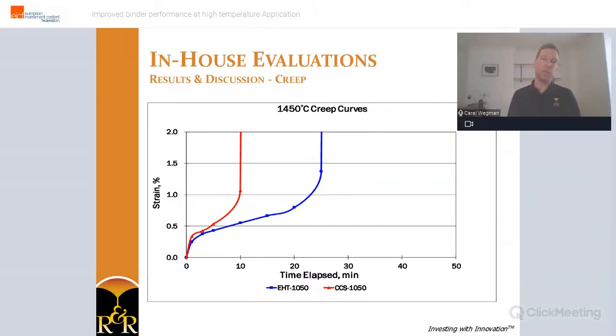So this portion of the creep data was obtained at the high test temperature of 1450 degrees C. In this graph, I only show the data for the samples fired at 1050 degrees C, but it represents the data in general. Both binders show a catastrophic failure. That being said, the EHT sample failed 15 minutes later than the CCS binder, indicating it has better creep properties. It must be noted that the stress level applied was 120 psi. This is considered very high. We chose this high stress to see clearly the differences between the binders. For any test temperature that we performed, it took the EHT sample longer to reach a given strain or deformation than the CCS sample.